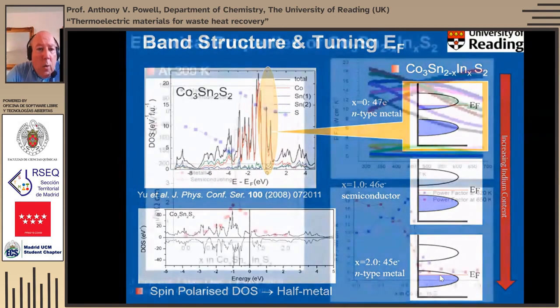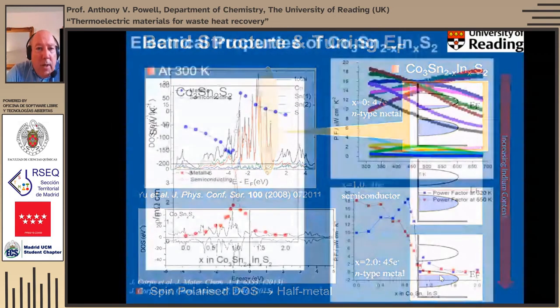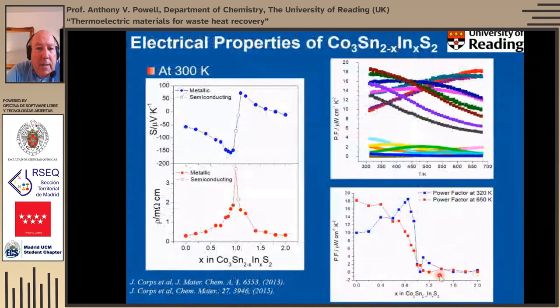So rather than showing all of the properties, I thought I'd just summarize really what's happening as we replace tin with indium here. What we find is that our Seebeck starts to increase as we move towards a more semiconducting region where the upper band is empty and the lower band is filled. Our resistivity also increases. And in fact, when we get to that 50-50 mixture of tin and indium, we do see at that point and just beyond, we do see semiconducting behavior, and then we come back out the other side and it becomes metallic.